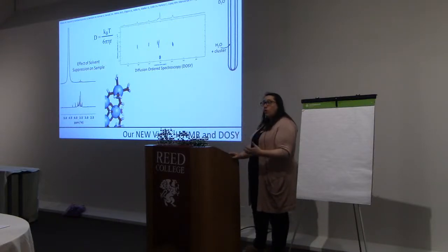So the other type of experiment that I can do to help confirm which cluster might correspond to these signals is diffusion ordered spectroscopy. So using the NMR, you can do a series of different gradient strength pulses, and then I'll show you on the next slide how it fits, but what it tells you is the diffusion rate. So as we move down, I know those are small numbers, but as we move down, things are moving quicker. So here's our proton NMR at the top. This is telling us the rate of the species diffusing. And so the faster something diffuses, the smaller it is. And the slower something diffuses with Brownian motion in solution, the larger it is.